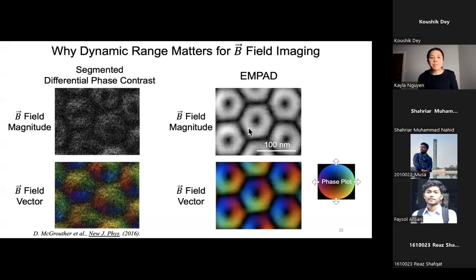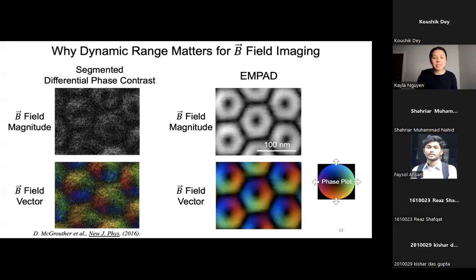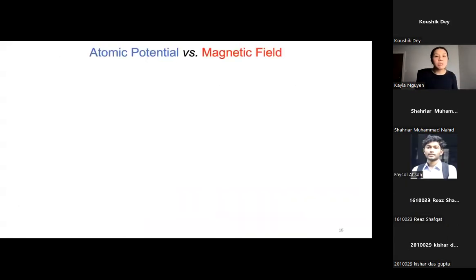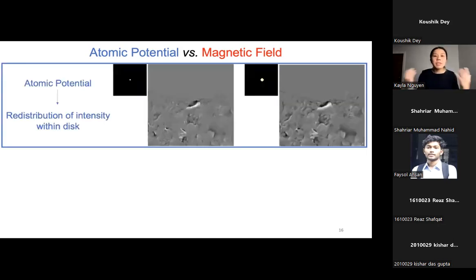Okay, so that's really cool. But in the next part of my presentation, I'm going to talk about why it also matters, especially when you don't have a perfect single crystal, but when you have grainy structures. One of the ways that we can do our imaging is in the presence of non-perfect crystals, not single crystals. If we take a layer of our B20 iron germanium and sputter it on top of a silicon film, it intrinsically forms these polycrystalline grains. What we want to know is how we can extract information from the grain and disentangle it from our magnetic field. So we look at the diffraction pattern here.